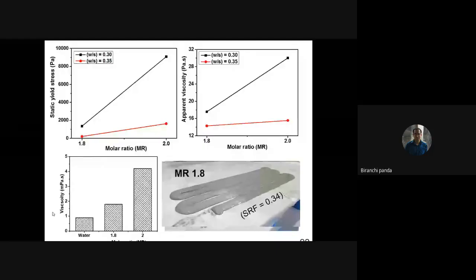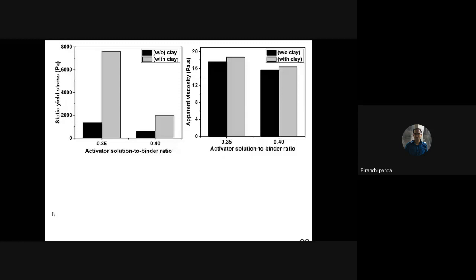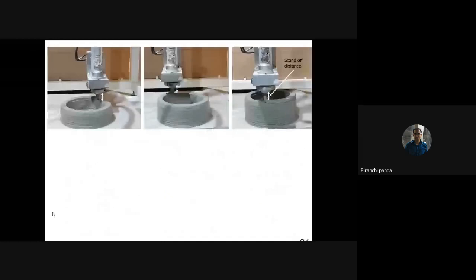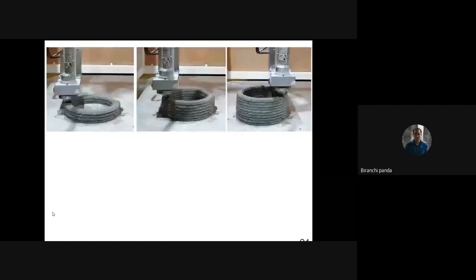Then again, we took the help of nanomaterials. We improved the material combinations by changing a lot of parameters. We did a lot of chemical tests that I don't want to explain in this slide. But what is the key improvement that we found? During printing, if you don't use any nanomaterials, or simply use the control mix, after printing some layers you will see some deformation. But with the improved material combination, we can see that the material is not deforming, because there is no gap between the extruder tip and the material. In the initial picture, you might have seen there was a gap between the top layer of the material and the nozzle. But in such cases, we don't have any gap between the nozzle and the material. So it means my machine is moving according to the G-code, and the material is not slumping at all.